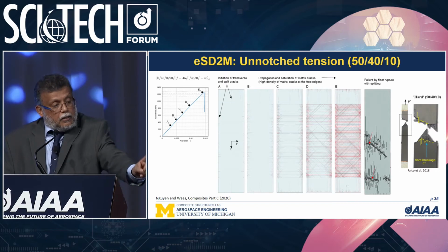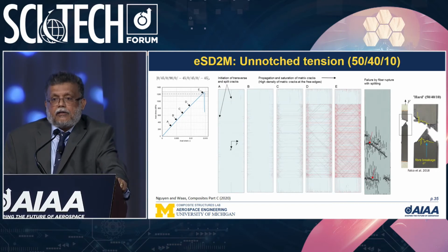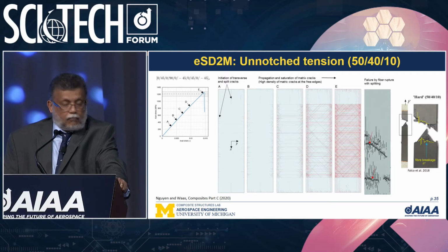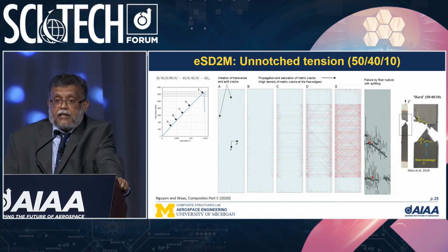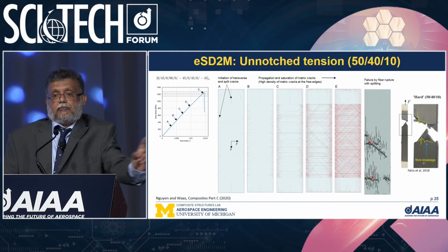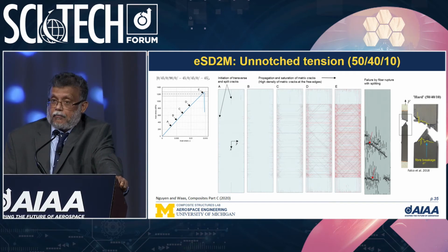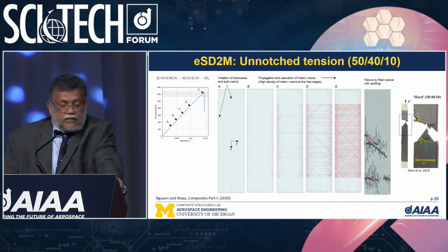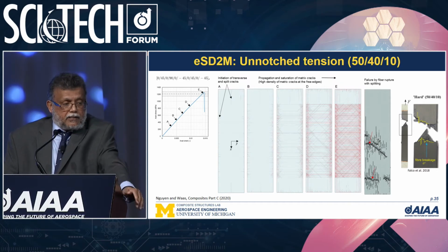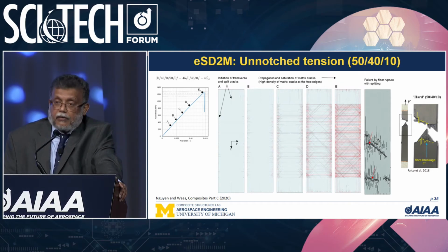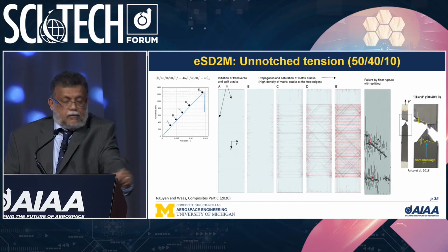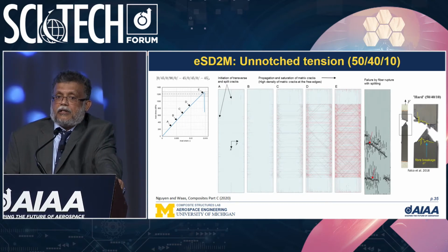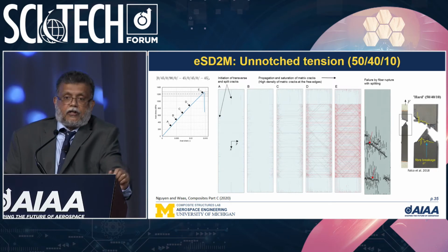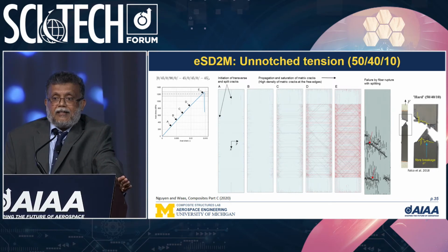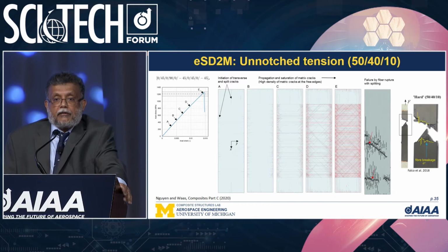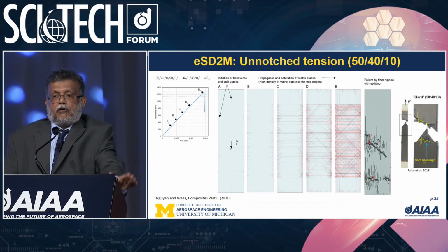The details such as edge cracking that you see in the second picture in this quasi-isotropic tension test, which is real, is captured in the ESD2M model. The increasing crack density is captured, the splits in the zero fibers are captured, and finally the failure of the laminate, which occurs when the zero fibers rupture, is also captured, where the failure plane is not perpendicular to the load direction.